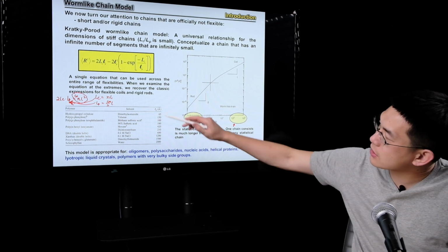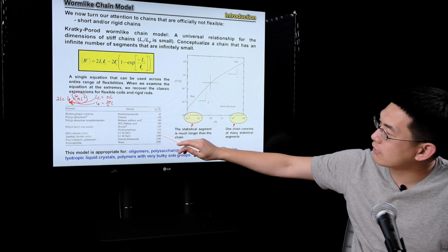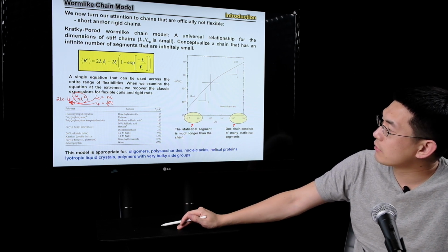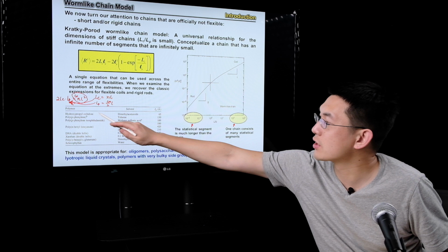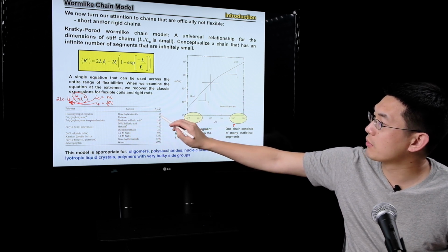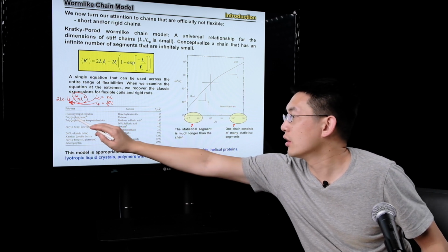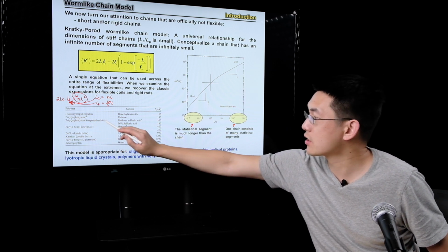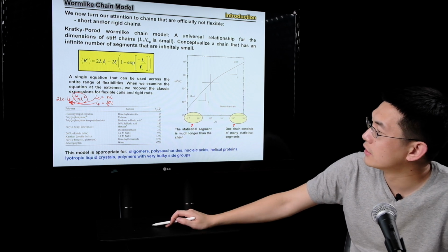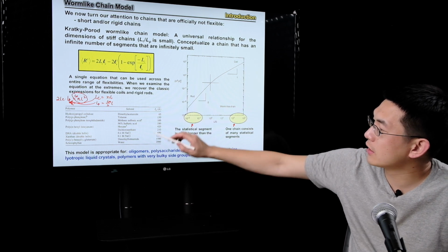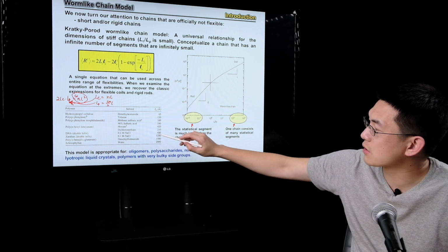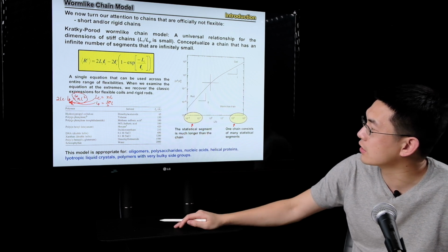We already discussed several of these chain models and what their persistence lengths would be. We can read it one more time. You have cellulose, which is some sort of semi-rigid chain, to polyphenylene, which is a conjugated polymer. You can see LP is about 13 nanometers. And you have other semiconducting polymers. But something useful is DNA. This is about 60 nanometers, as you can see.